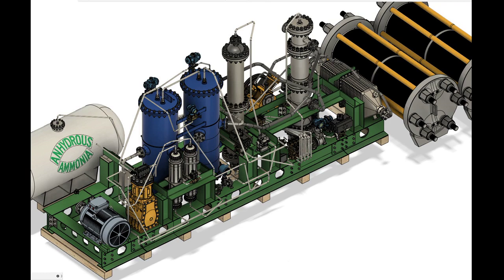Since the early experiences at BASF, carbon steel was abandoned as a structural material in favor of ultra-low carbon alloy steels. Many early reactors made use of a design where the load-bearing pressure vessel walls made use of low-carbon steel, but a carbon steel layer was placed on the inside, to bear the brunt of the hydrogen attack and decarburization. A novel design in the future may be the use of a ceramic liner on the insides of the reactor wall and heat exchanger tubes, shielding the ferrous material from the hot reactant products. With the availability of modern low-carbon nickel-chromium alloys, hydrogen attack becomes less of a concern than during the initial development stage.